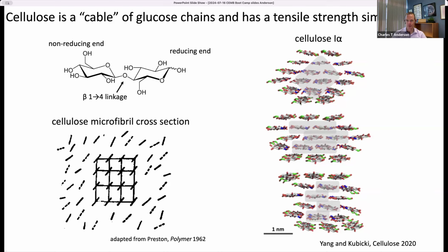So a 2-3-4-4-3-2 configuration, a 3-4-4-4-3, or a 3-3-3-3-3-3-3. So these are different hypothetical configurations of the glucan chains in the cellulose, and there's actually debate still in the scientific community about what that configuration is in real life. For a long time, cellulose was thought to have 36 chains and be quite large in its cross-section, but more recently, there's been a hypothesis that it contains somewhere between 18 and 24 chains in cross-section.